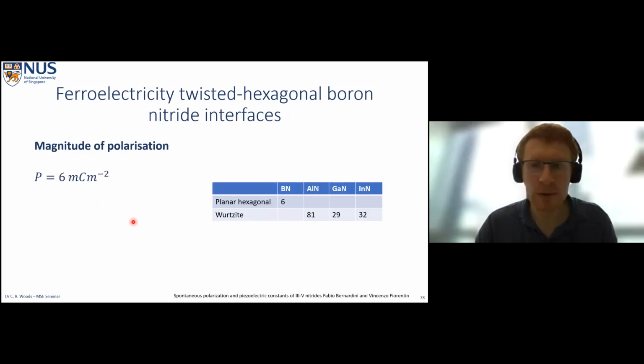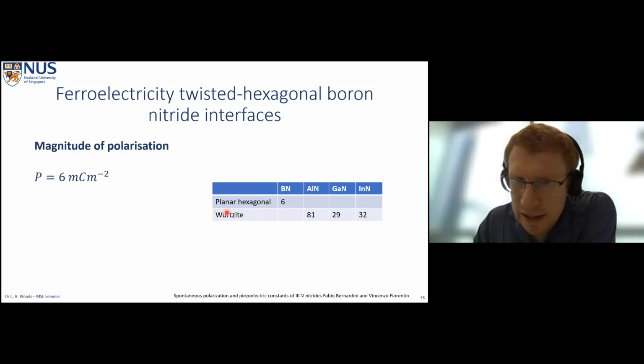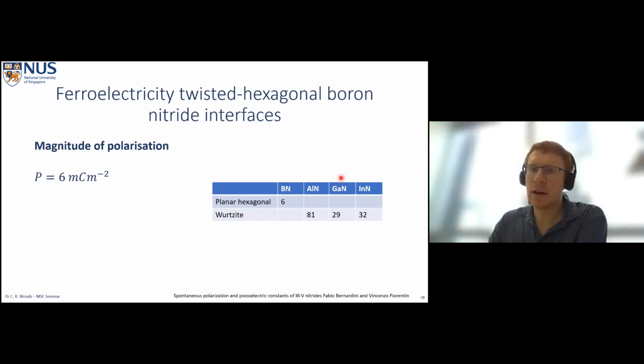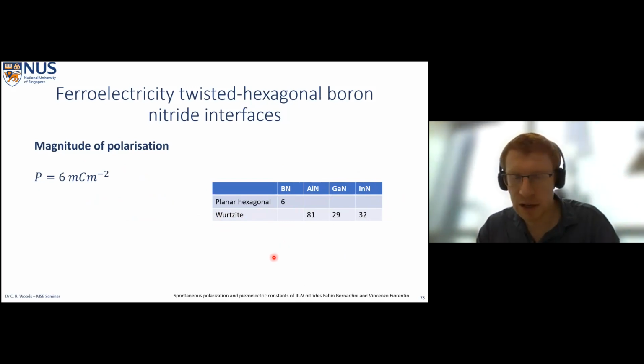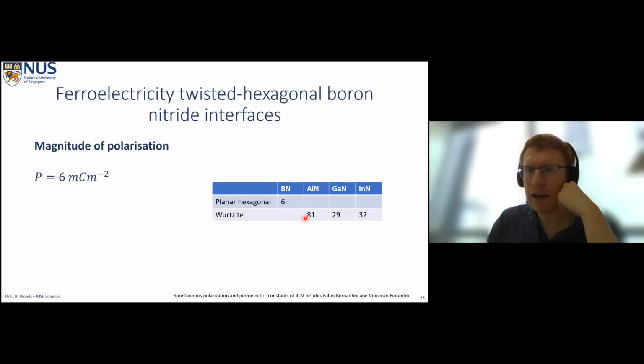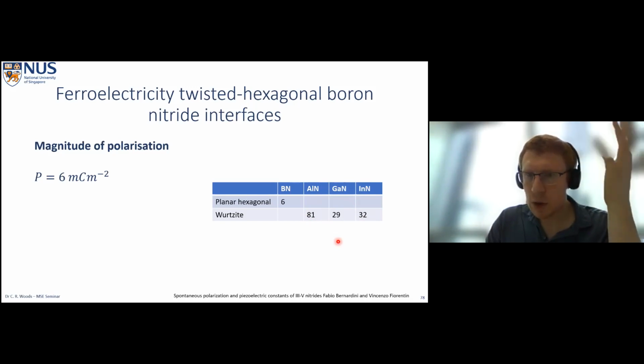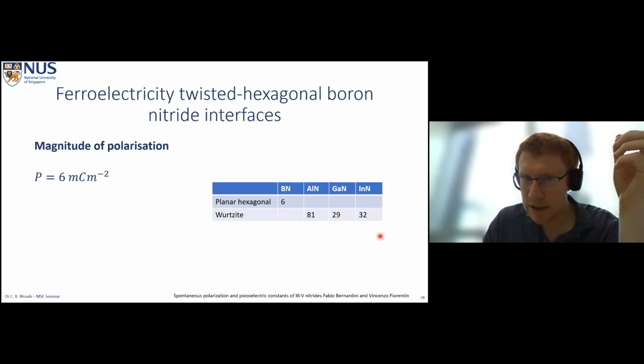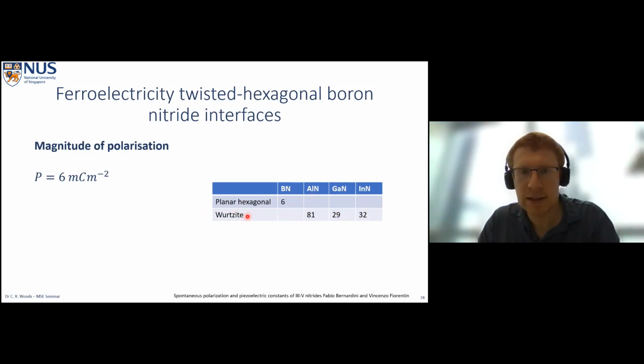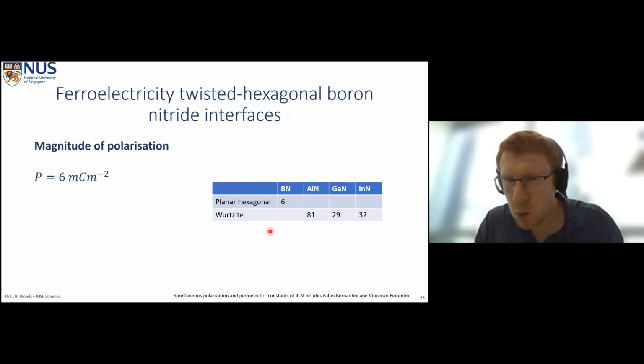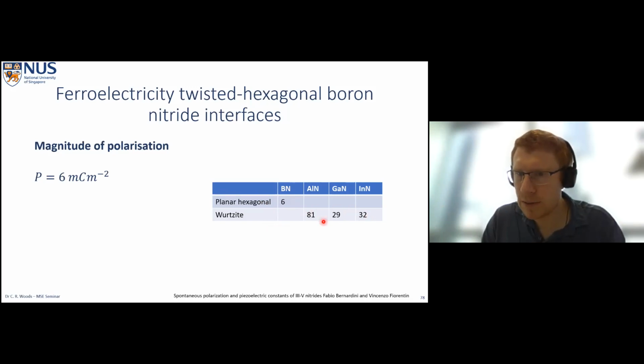And the last thing to do, I don't want to overrun on my time, is just to compare. So we looked at the wurtzite form of boron nitride, and we can compare to the other common Group III-nitrides, which have polarizations in their wurtzite form, and compare the magnitude of our polarization to theirs. And so if we look at aluminium nitride, gallium nitride, and indium nitride, we're actually not doing too badly, because this is within an order of magnitude of the average of these three, which isn't too bad because these are actually wurtzite. Right, so this is a structural change which produces this displacement of atoms out of the plane. Wurtzite is a sort of tetrahedral form of stacking, whereas planar hexagonal is, of course, planar. So we wouldn't expect to have a polarization which would even be comparable to these.